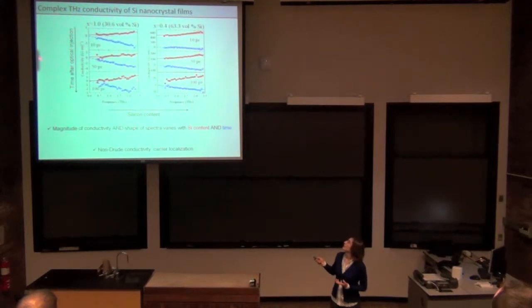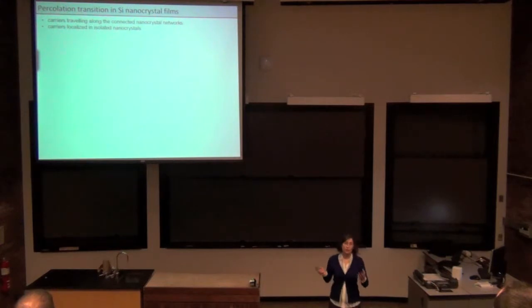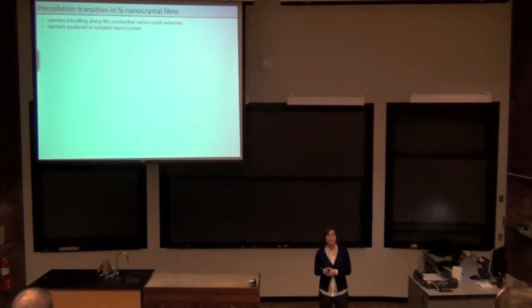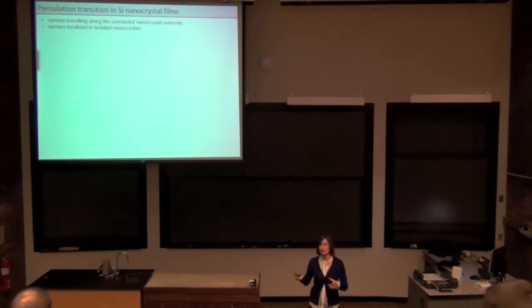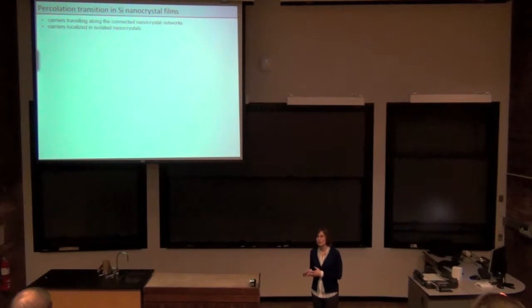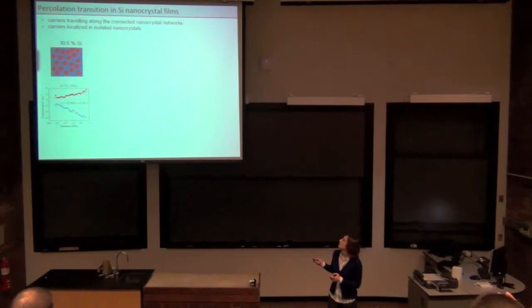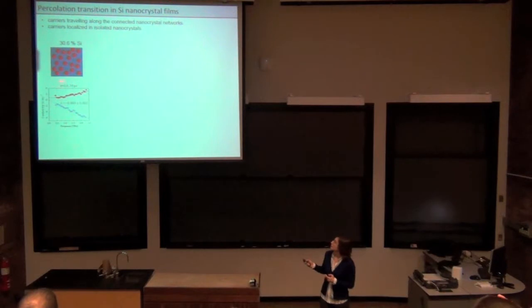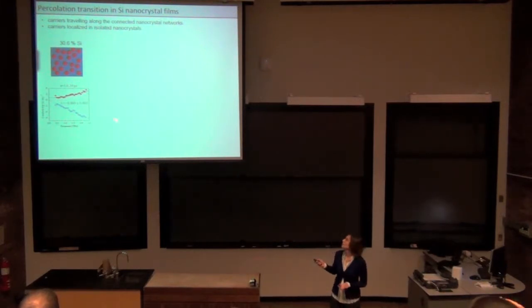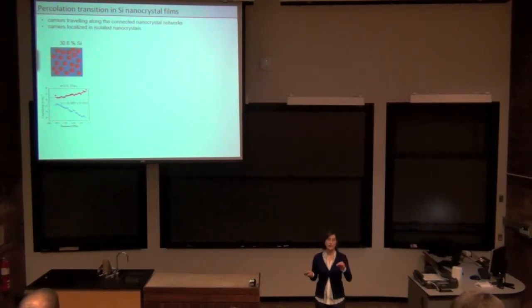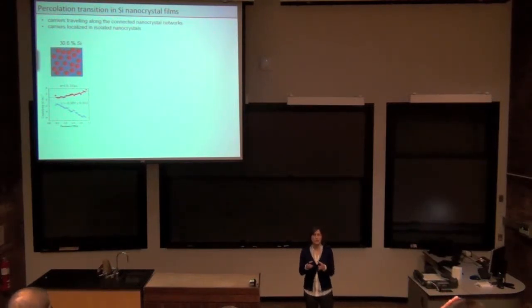Let's first look at the changes along this silicon content axis. We know from the TEM that each sample contains some distribution of isolated nanocrystals and some that are connected together in pathways, but our terahertz probe pulse samples the entire array, so we get some sort of average response. For example, in the 30% silicon at 10 picoseconds, we get this conductivity, which is described by this localization parameter very close to negative 1. Remember, negative 1 is complete localization in these grains.